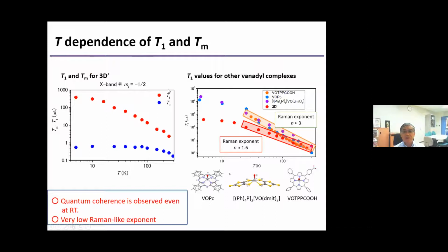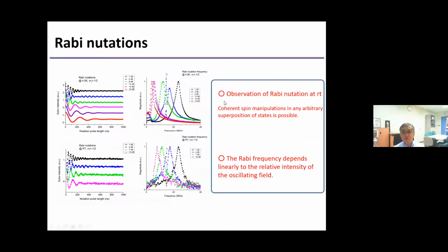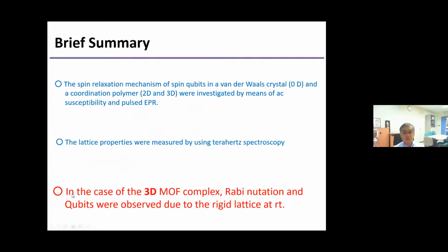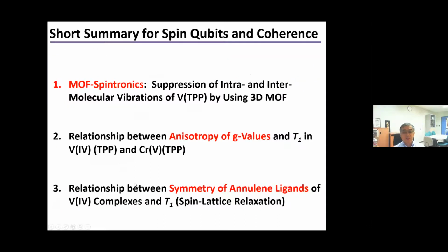This is the temperature dependence of T1 and Tm. You can see that even at room temperature, quantum coherence is observed. And also Rabi nutation: we observe the Rabi nutation even at room temperature. And the Rabi frequency depends linearly on the relative intensity of the oscillating field. So a brief summary: in the case of the 3D MOF complex, Rabi nutation and qubits were observed at room temperature due to the rigid lattice. So I skip the second and third topics.